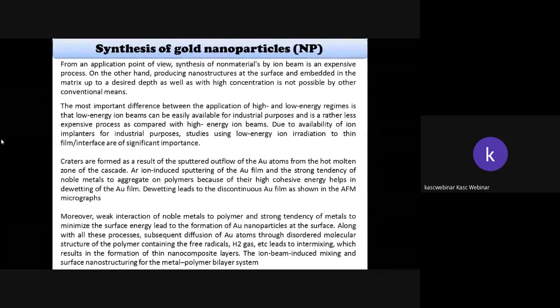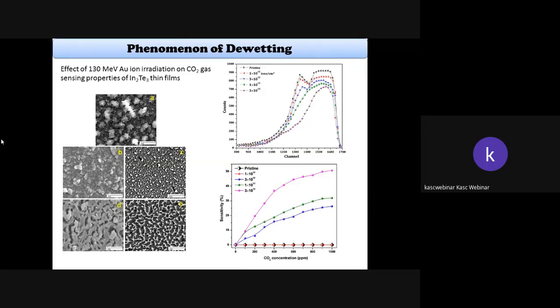Moreover, the weak interaction of noble metal to polymer and strong tendency of metal to minimize the surface energy lead to the formation of gold nanoparticles at the surface. Along with all the process, subsequent diffusion of gold atoms is also possible through that PET layer, through the disordered molecular structure of the polymers containing free radicals, H2 gas, etc., leading to interface mixing, which results in the formation of a thin nanocomposite layer. The ion beam induced mixing and the surface structure for the metal polymer bilayer system is a new one. And what was that? The peculiar phenomenon that's called dewetting.